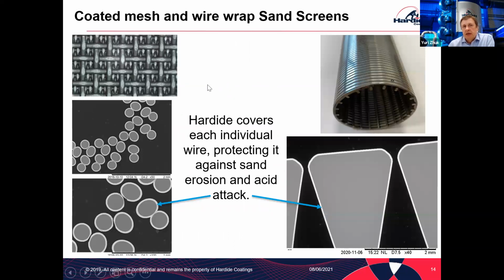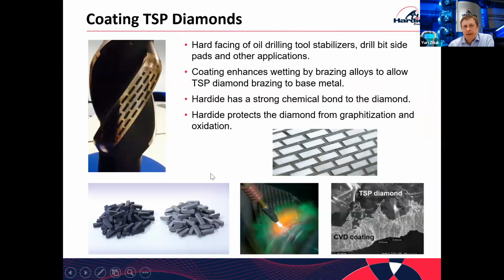This is quite an interesting slide showing 2 types of sand screens that we coat. The photos on the left show the mesh sand screens. You can see that in the cross section of the coated mesh, the coating surrounds each wire. On the right, that's a wire wrap type sand screen. And again, the coating is a white layer surrounding that profile wire. And by this, the coating protects the wires and the sand screens against erosion and also against acid attack.